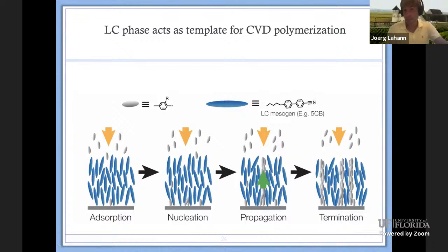So if that's true, there should be some interesting things coming out of this. Number one, if it's really like that, then the elastic energy of the LC should influence the morphology and the diameter of the fibers. Number two, depending on where the defect lines go, we should get different shapes of fibers as well. If you move from a nematic to a cholesteric phase, you should change that. So you should have very nice control over both the diameter and the shape of the fibers if those mechanisms hold.